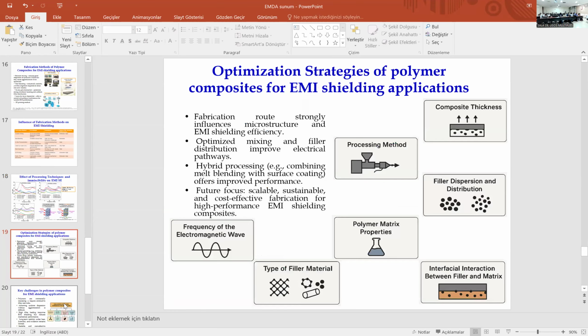If you look at the optimization strategies for EMI shielding performance, the performance of the polymer composite is strongly controlled by how well the conductive fillers are dispersed, how effectively they bond with the polymer matrix, and the microstructure that forms during processing. Achieving high shielding levels, typically above 40 to 60 decibels, requires carefully optimized fabrication techniques and filler design strategies. Future research is moving toward hybrid filler systems, 3D engineered conductive networks, and environmentally sustainable conductive polymers.